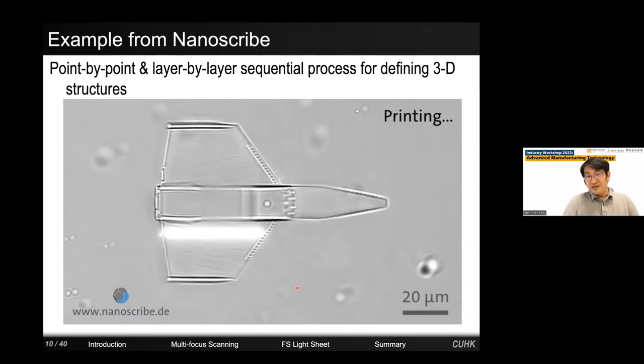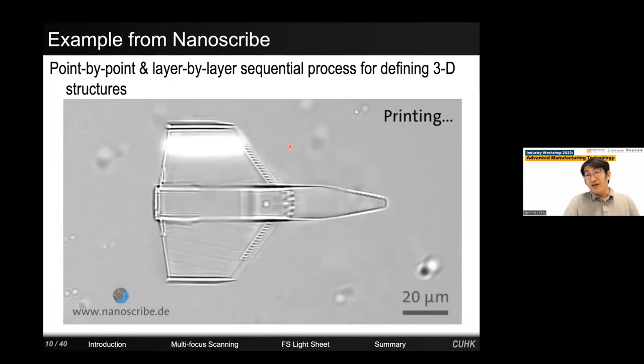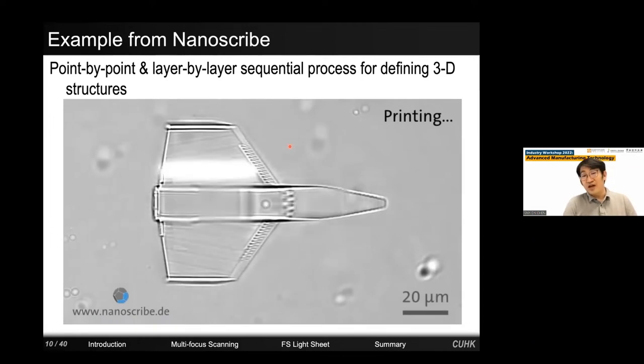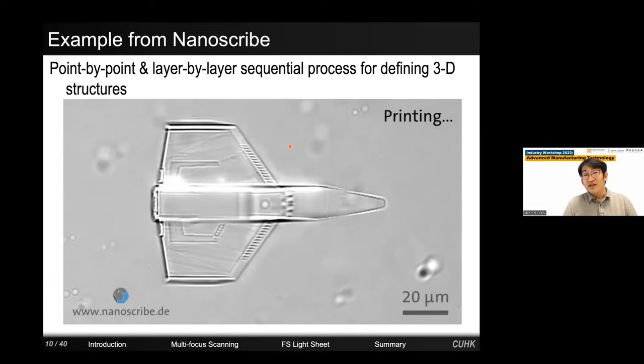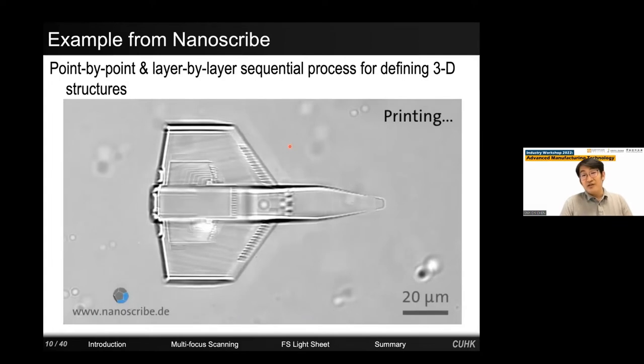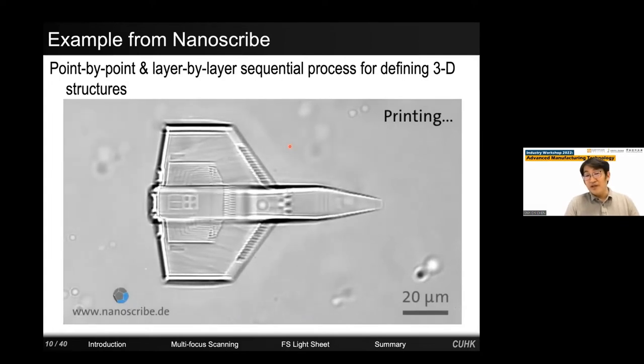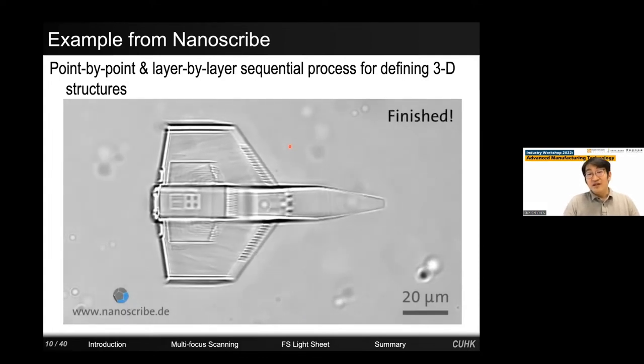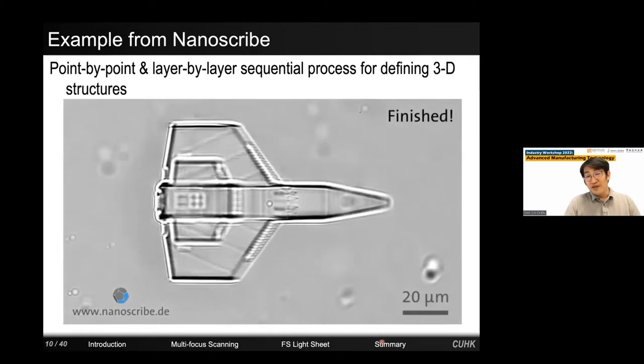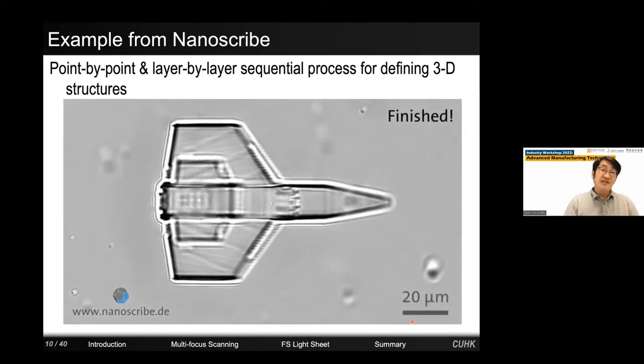And let me talk about more of the process. During the printing process, the objective lens is immersed in the photoresin, which is in liquid form and has a refractive index of 1.5. So in order to ensure high resolution, a matching index objective lens is used. It's typically an oil immersion lens. After fabrication, you take out the sample and develop it, and you can visualize the result in high resolution in an electron microscope, as shown here just now.